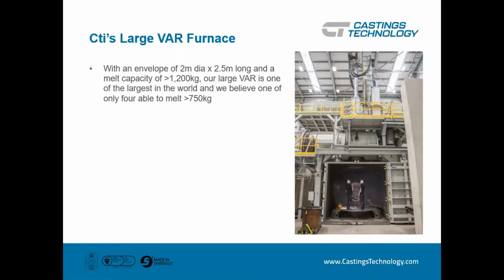At that point, we're using the princely sum of about 40 volts of electricity, but at 40,000 amps. So for those of you good mathematicians, that's about 1.6 megawatts. We're going to be pulling that for around 20 minutes to get the melt pool that we need. Then the computer cleverly and simultaneously withdraws the electrode, which has been moving up and down to maintain the gap, but also, as the crucible fills up, it needs to retract. It fully retracts, which allows the crucible to tip. It pours the material down through an opening here and into the pouring chamber below.